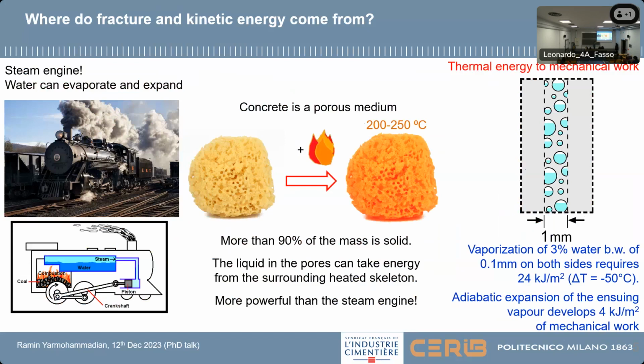If you just want to know the magnitude, you can see, okay, for vaporization of just 3% of water by weight in 0.1 millimeter, a very superficial layer on two sides of the crack, we need 24 kilojoules per square meter, which is equivalent to a 50 degrees Celsius temperature drop. That is okay, because we have like 200 degrees Celsius there. So if you lose 50 degrees Celsius, it's fine. We are still above boiling water temperature. And then that expansion can give us 4 kilojoules per square meter. So you can see easily how this conversion can go.